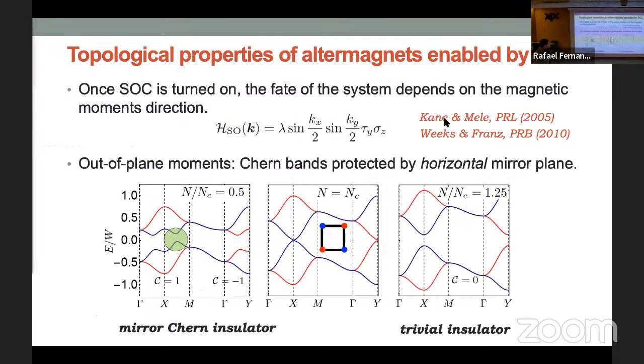Okay? But now what happens the moment I turn on spin-orbit coupling? Well, it gaps this Dirac point, and you now get Chern bands. These Chern bands are actually protected by a mirror symmetry, these horizontal mirrors, when the moments are out of the plane. So if I have this band structure here and I place my chemical potential at zero, for example, I'm going to get a quantum spin Hall effect, a quantized quantum spin Hall effect. This is a mirror Chern insulator. But importantly, this happens if the magnetization is not too large, and if the moment points out of the plane. Essentially, this spin-orbit coupling term here has the same role as the Kane-Mele term in graphene.